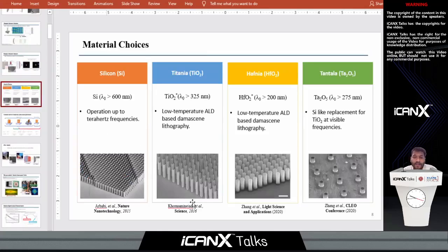The reason you see surface roughness is because these are high index dielectric pillars on a low index substrate, silicon dioxide. So we coat them with aluminum or E-spacer to take SEM images. And so it's really an issue of taking scanning electron microscopy images. But the underlying pillars themselves are quite clean. I apologize, I didn't make that clear. Oh, okay, that's good. Thank you very much. Mostly to take SEM images, we put a conductive layer on top. Okay. So that kind of makes it look like that, right?